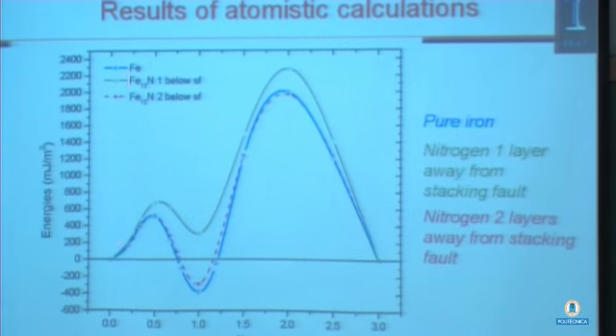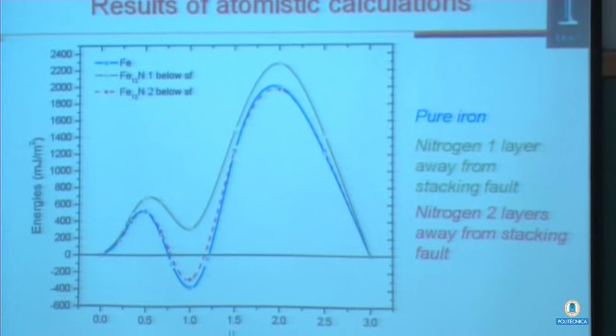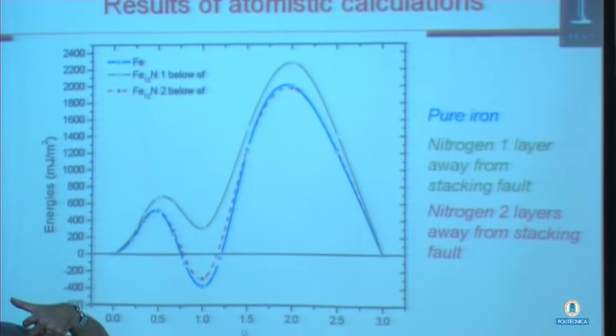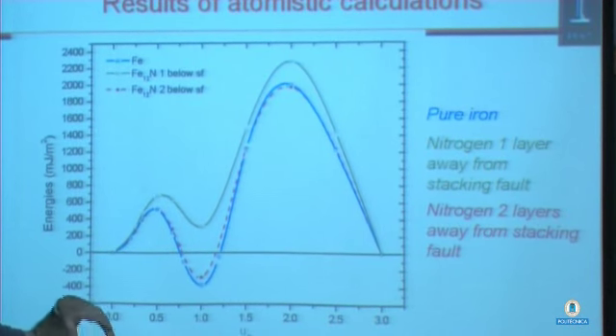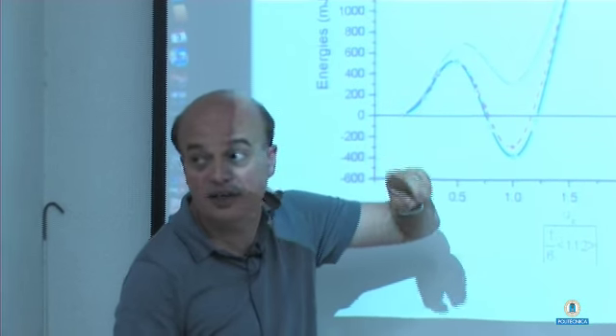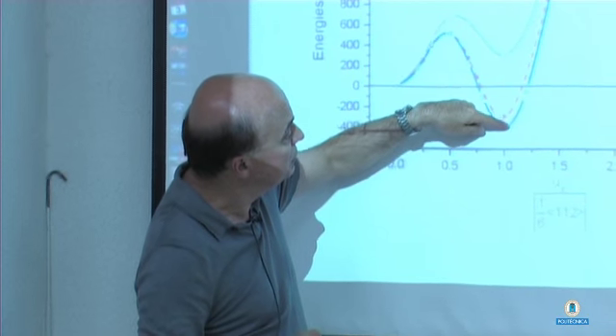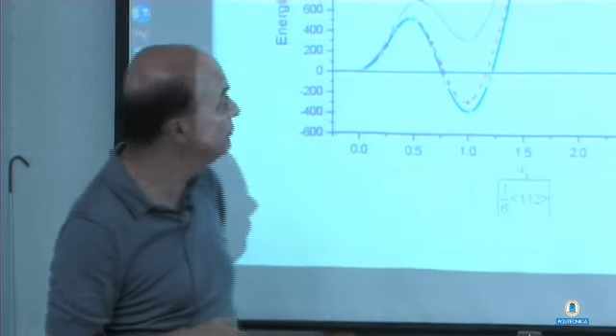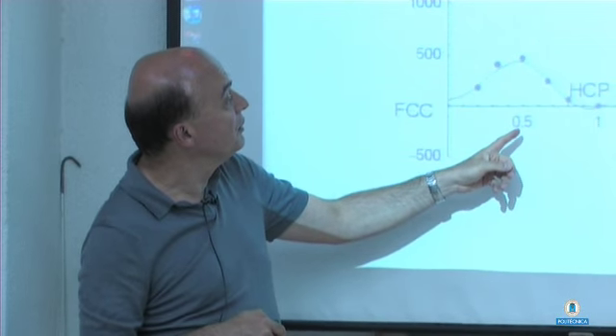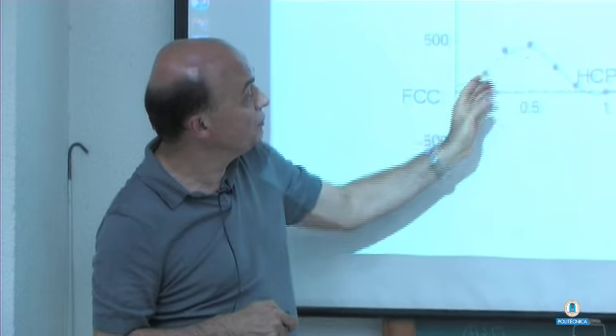So you do first iron, you add nitrogen, you get modified curves, of course. If you do pure iron, it looks like this. This is FCC iron. If you keep adding nitrogen, this peak goes up. This level goes up as well. So if you keep adding nitrogen, the curve gets modified. Again, the same idea. If we minimize the energy, we can get a closed-form solution for the stacking fault width.